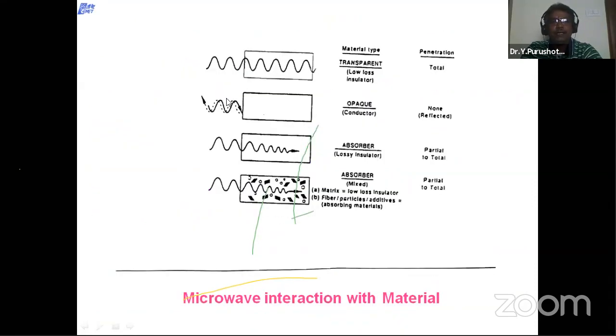And here one can see microwave interaction with the material. Depending upon the material type, if the material is transparent, microwave penetration will be total. If a material is a conductor, like metal, microwaves don't penetrate; they reflect back. If it is a lossy insulator or absorber type of material, absorption is from partial to total. For a mixed material, again it is partial to total. So microwave heating is totally material dependent.